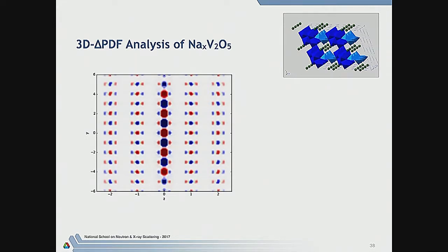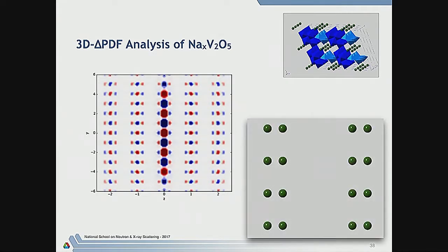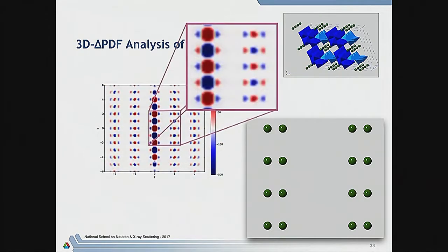Okay. Now we have these weird three-rung ladders. So what does that mean? We have two-rung ladders of sodium in real space, but when we look in PDF, we seem to have three-rung ladders. And the reason is quite simple: we don't know what is the phase of that interatomic vector. So we have to consider that there are interatomic vectors which arise from a sodium ion that happens to be on the left rung that couple it to the right rung. So here we have a sodium ion, for instance, and we're saying there's a probability that there will be another sodium ion at this vector away on the right-hand rung. In this case, this probability is red. It's greater than average probability. Whereas this probability is blue, which means it's very unlikely that you'll have a sodium there.